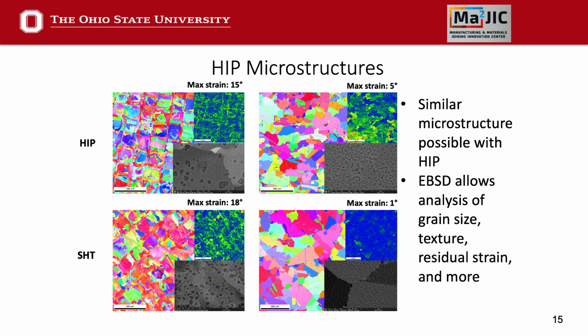We have more of a bimodal precipitate structure, and then we have still pretty high strain in the material, which you kind of develop during printing. In the supersolvus condition, we recrystallize the grain, so we have an equiaxed grain structure, pretty low strain in the material, and then we were able to get kind of a fine homogeneous precipitate structure, which is something we're able to control, the size of that structure, with the cooling control available through HIP.